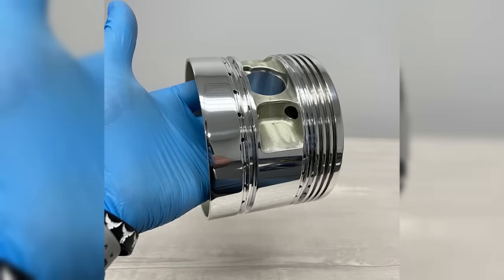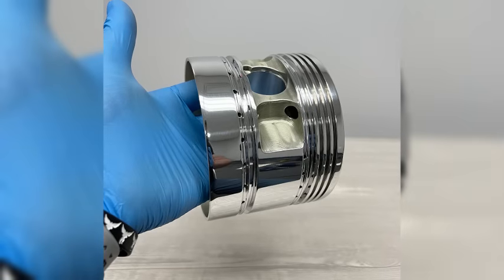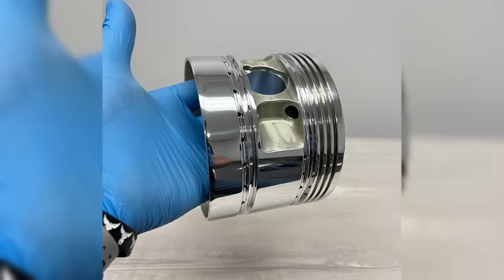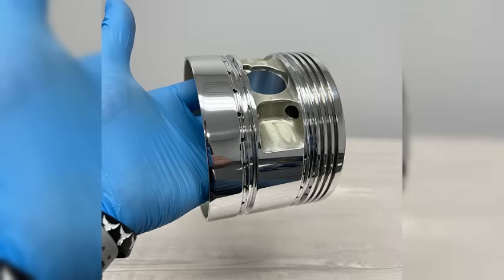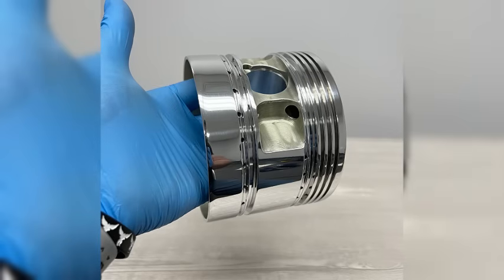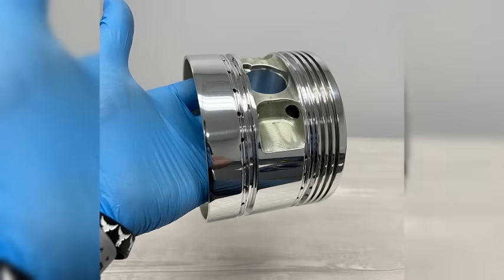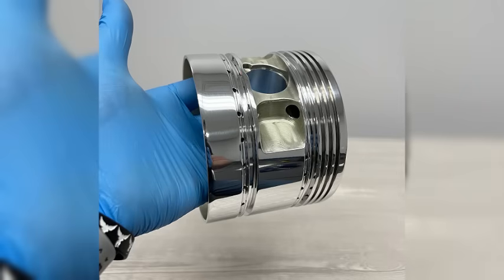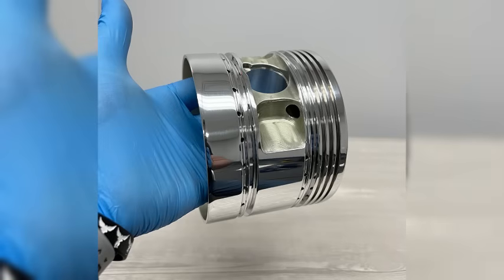Aircraft engines were entirely different. The Merlin produced 1,400 plus horsepower from 1,650 cubic inches. It ran at 3,000 RPM continuously, with short bursts to 3,600 RPM. Specific output was nearly triple that of automotive engines. Everything ran hotter, harder, faster. American piston ring manufacturers had never built rings for these conditions because American aircraft engines of the 1930s were relatively low-output radial designs that didn't push the limits the same way.